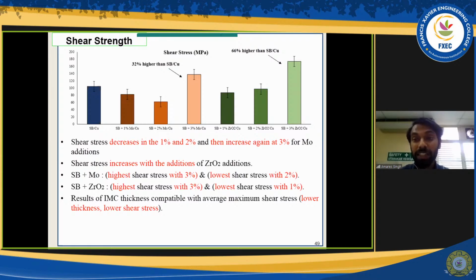So it actually gives another strengthening effect to the shear strength. So this has to be tallied with the thickness as well. So we could say here that the higher percentage of shear strength was observed for the 3% of zirconia. So this is actually very high, or quite to say more than half of the SB/Cu.